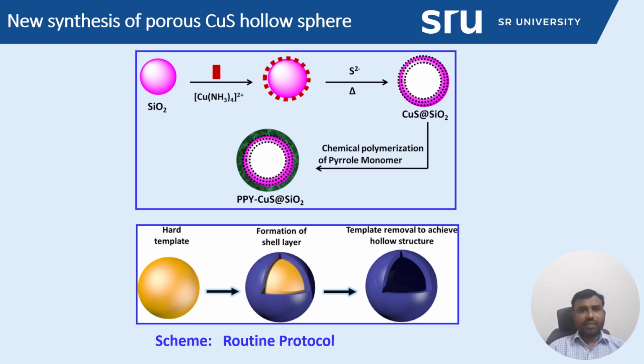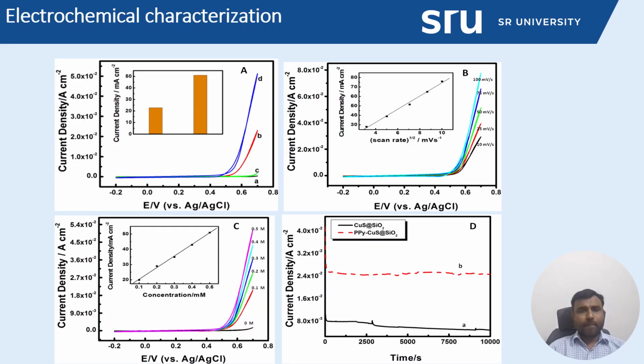So it is a significant advantage without using any toxic chemical or any expensive reagent. Simply we use SiO2, copper acetate and ammonia solution as precursors and apply thermal treatment under hydrothermal conditions. We achieved highly uniform copper sulfide spheres. So what will happen? The obtained material is coated over the glassy carbon electrode surface. Glassy carbon is broadly used as a working electrode because it is a good conductor with a smooth surface.